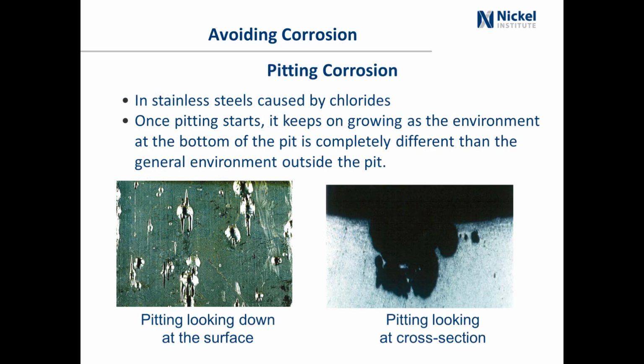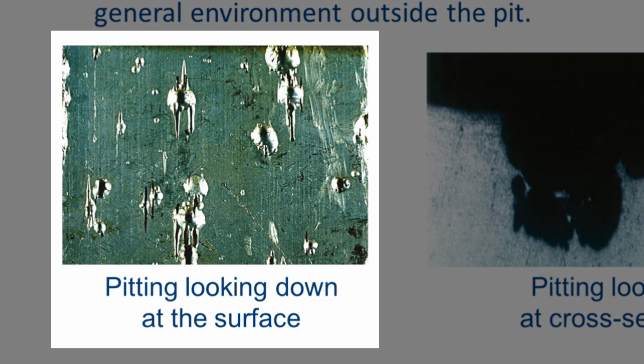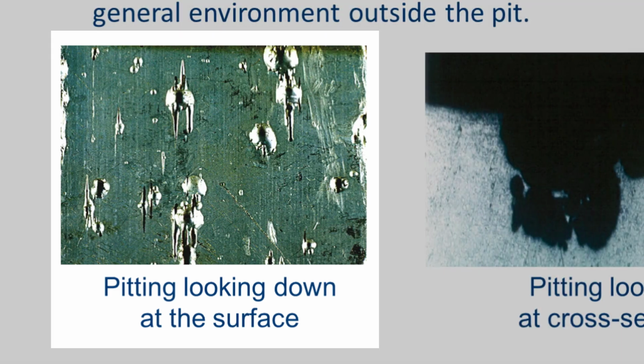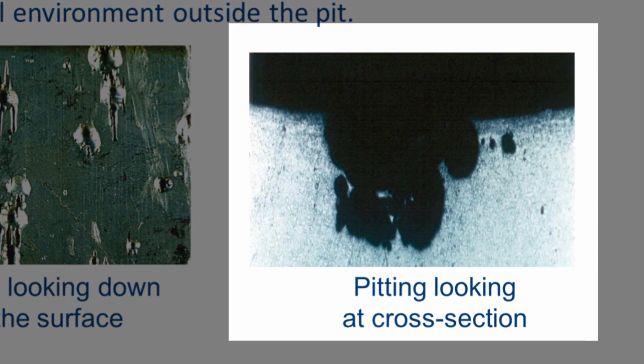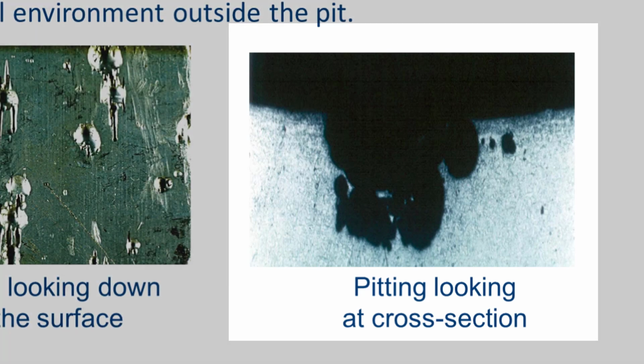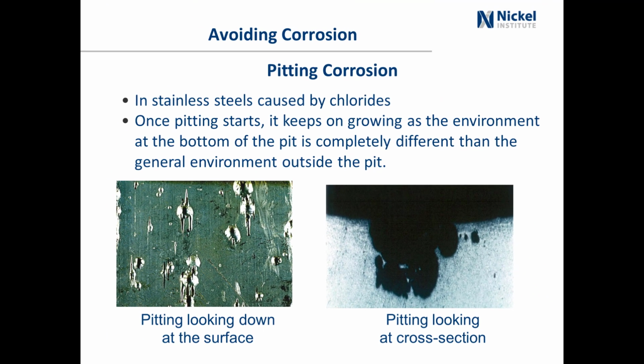So in the case of pitting corrosion, at least in a food contact application, in stainless steels, pitting corrosion is generally caused by the presence of chlorides. And we have a picture here showing some pits that are formed on the surface of a stainless steel, looking down on the surface. And then here's a cross-section of a pit. Once pitting starts, it keeps on growing, as the environment inside the pit is completely different than the general environment outside the pit, because it becomes more acidic inside the pit. In fact, you're producing hydrochloric acid inside the pit.